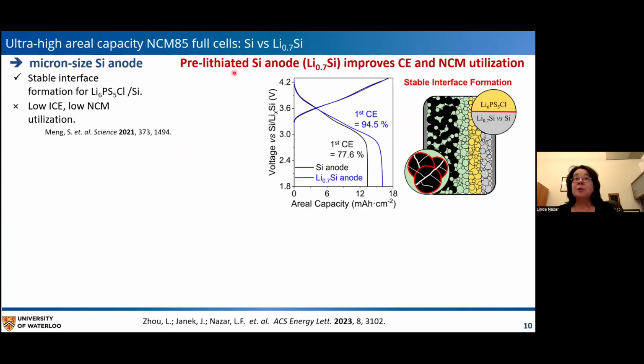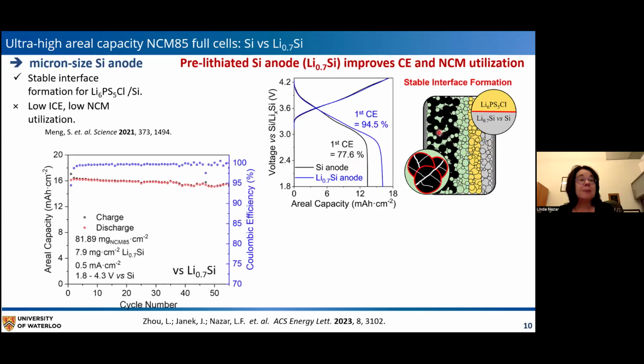So what we did was we pre-lithiated the silicon anode simply by a very simple reaction between the lithium and the silicon. And you can see that the initial coulombic efficiency is increased significantly compared to the silicon system. And so we ran cells then in this configuration, similar to what's shown here with the lithium silicon anode, a layer of argyrodite, and then our lithium metal halide as both our interface and also our catholyte.